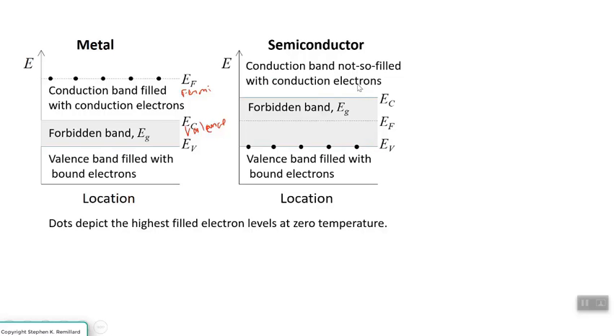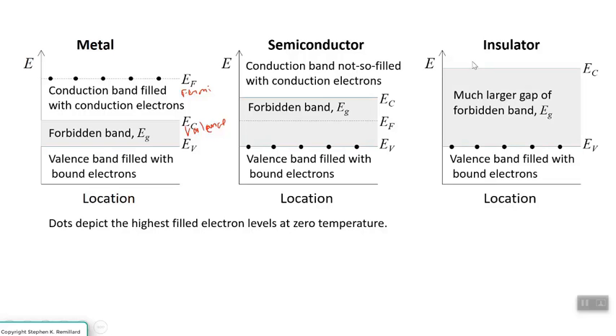And so a semiconductor is really an insulator, and in a sense, yes, except that the band gap is small enough that you get to room temperature. And some of these electrons will make it up there just by thermal agitation. They have enough vibrational thermal energy that some of them just make it up to the conduction band edge, and they stay there. They can move around. And so at room temperature, a semiconductor does have a little bit of conductivity for sure. If the band gap were bigger, you'd have an insulator.